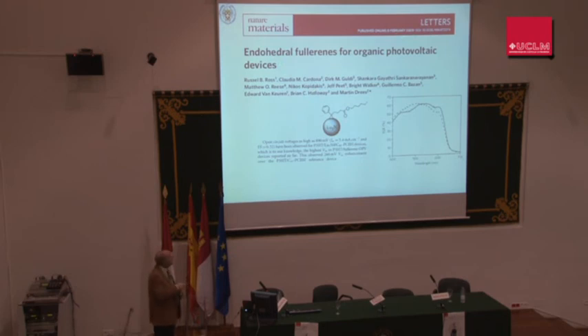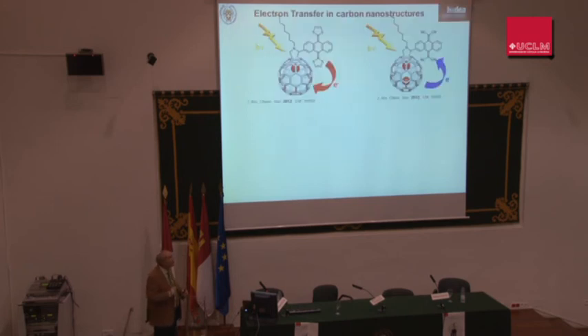February 2009, it was reported the first example having lutetium nitride, which is the analogous of PCBM, not M, this is another ester group. In this case, the efficiency was close to 5%, a little bit better than that for pristine C60. So this means that these materials are very appropriate also for photovoltaic purposes. Still, the main problem is the scarce amount available for these materials.